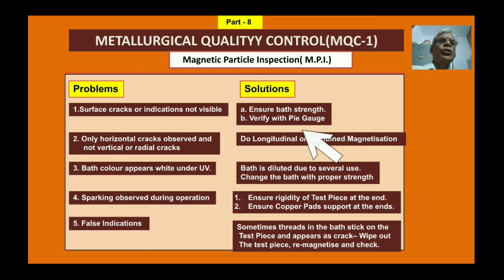Then the bath color appears white under UV. This is also one of the things which happens, and I have experienced this personally. Sometimes you see the bath gets a white or milky color, and you go on continuously using it. Why does it get a milky color? Because you are using it continuously, and in that case it sometimes gets adulterated with various outside elements, and then it gets a milky color. So you should not do that. You have to change it. In that case, the bath is diluted due to several uses. Change the bath with proper strength. You have to change the entire system, vacate that total system, that tank, and then fill it up with a bath of proper strength and confirm the bath strength through the centrifuge method which I have explained earlier.